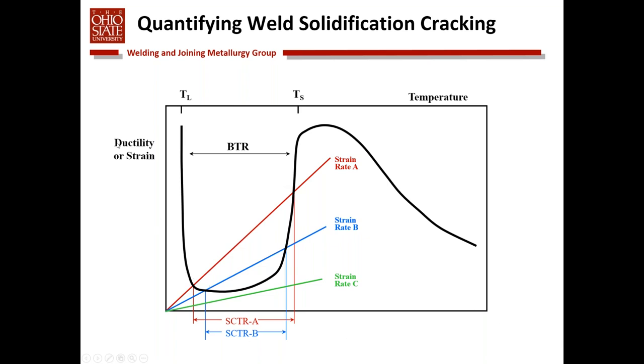And if we superimpose on this ductility curve the strains that develop during welding due to cooling and thermal shrinkage, depending on the strain that builds up, if the strain exceeds the inherent ductility of the material, as shown here in the red line and the blue line, we form a crack. If the strain is less than the inherent ductility of the material, it doesn't crack.